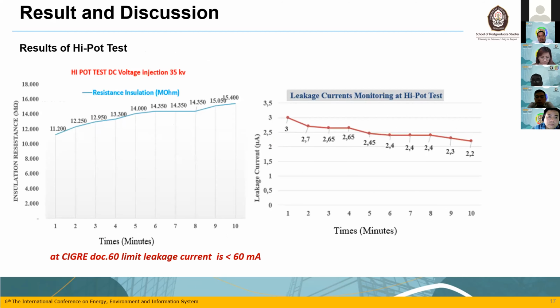And this is the result of hipot. This is insulation resistance with hipot, injecting 35 kilovolt direct current, and this figure shows leakage current monitoring at hipot. At CIGRE doc.60, the limit of leakage current is less than 60 milliampere.